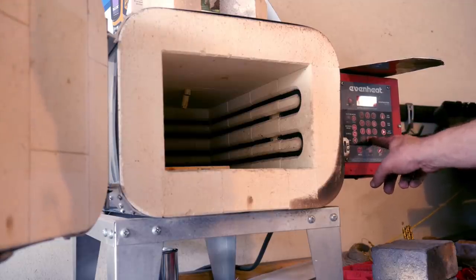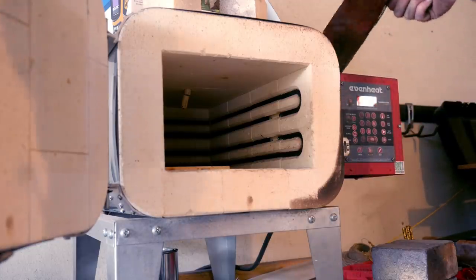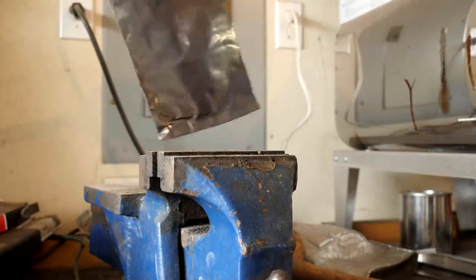It's time for thermal cycling. The forging is done. So I'm going to cycle it at 1,550 degrees for 10 minutes, then 1,500 degrees. Then I'll give it a relaxation cycle at 1,100 degrees and let it cool slowly.